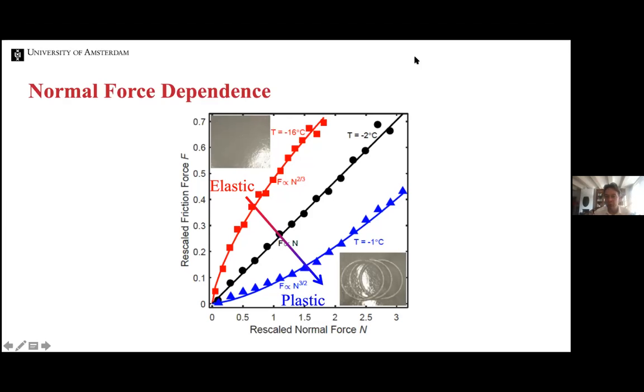It's actually too soft. So what we think is the specificity of ice is that it remains very, very hard, almost up to the melting temperature. It's only very close to the melting temperature that you get this plowing, and that's why you can skate. And so our feeling, but we're trying to quantify that, is that other materials already become soft way before the melting point. And then you always get plowing.